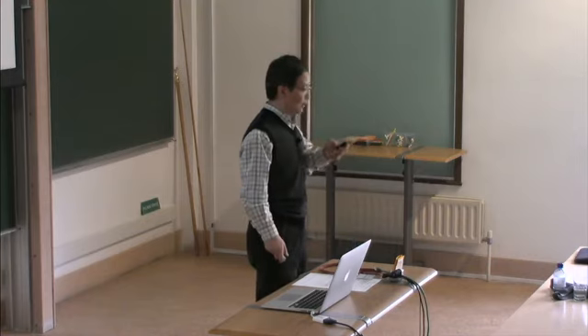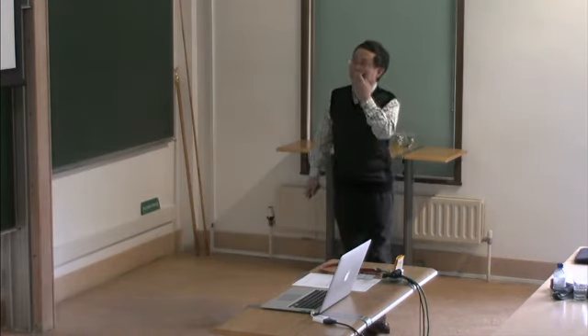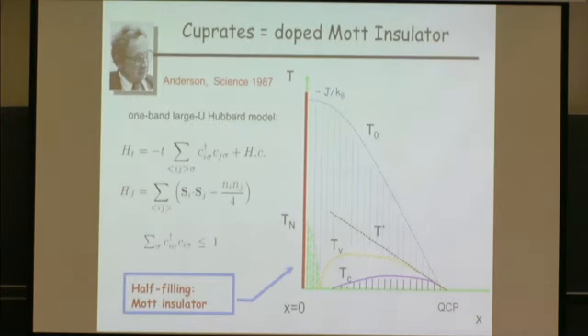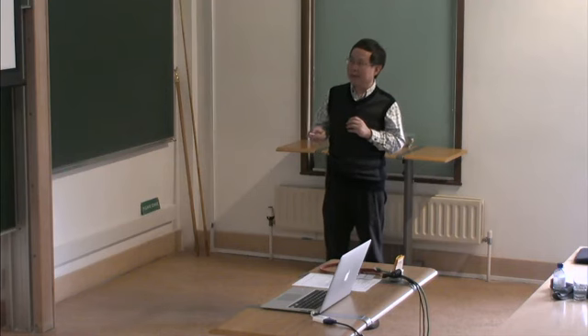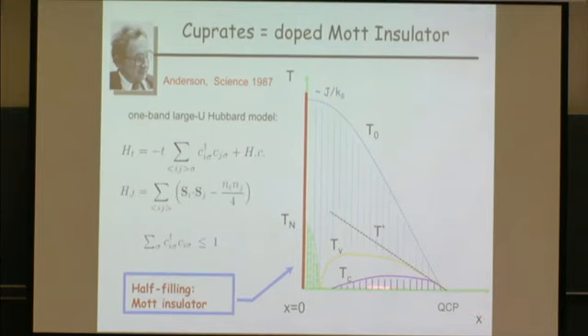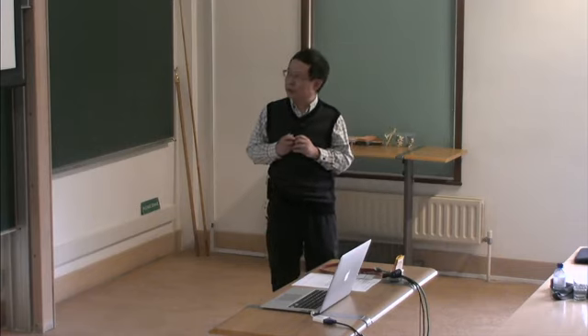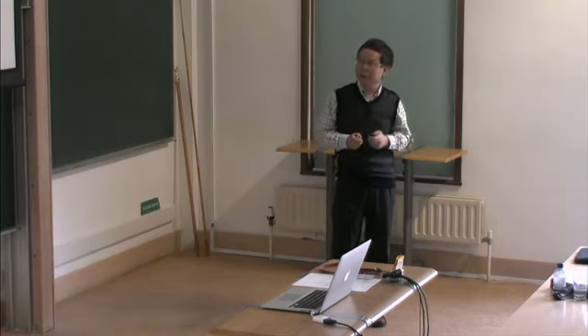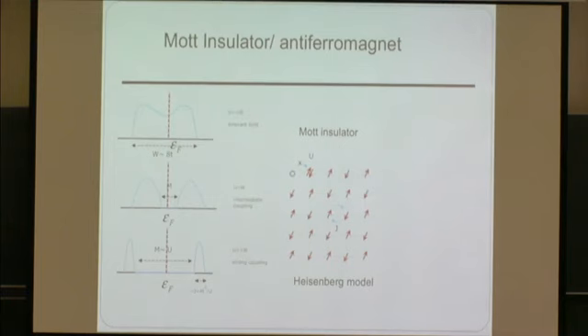This indicates that this system is a so-called doped Mott insulator. This picture was first advocated by Phil Anderson right after the discovery of the high Tc cuprates. According to his picture, a one-band, large U Hubbard model could describe this system, where at half filling this system becomes an insulator, but it is a Mott insulator due to interaction. Therefore, along the x-axis you measure the charge doping into such a Mott insulator, and this x will really play an essential role here.